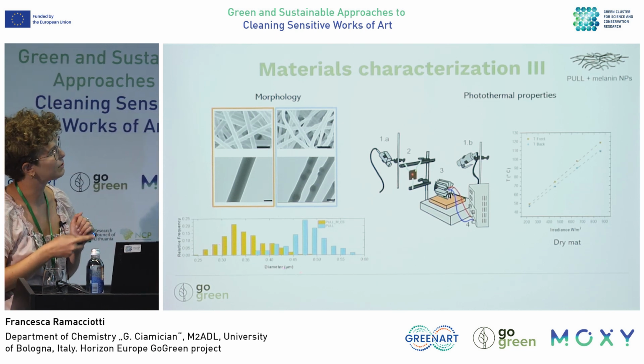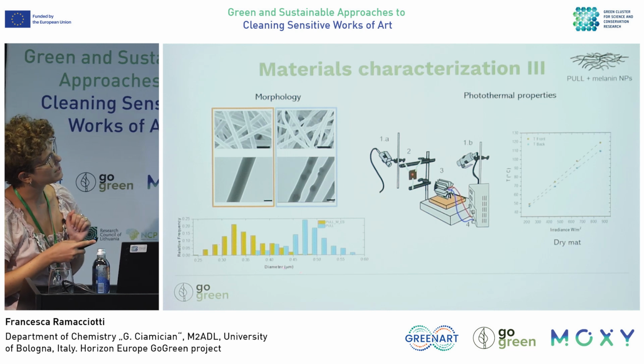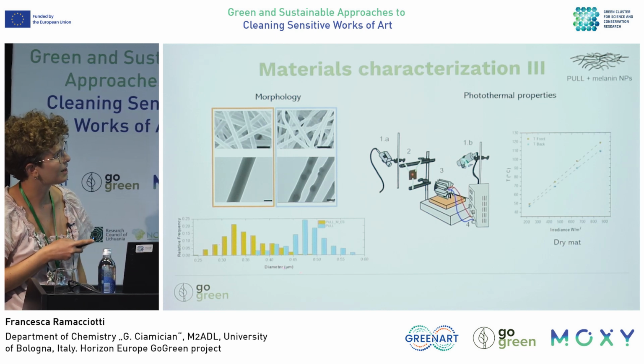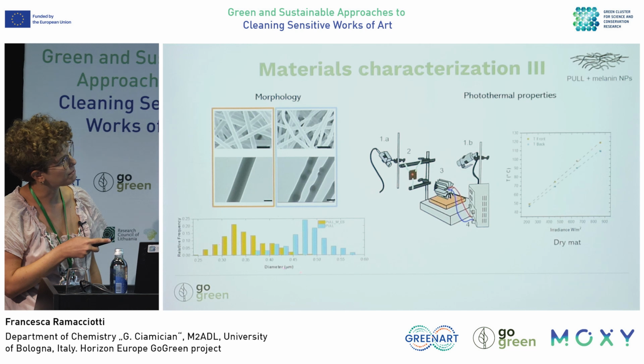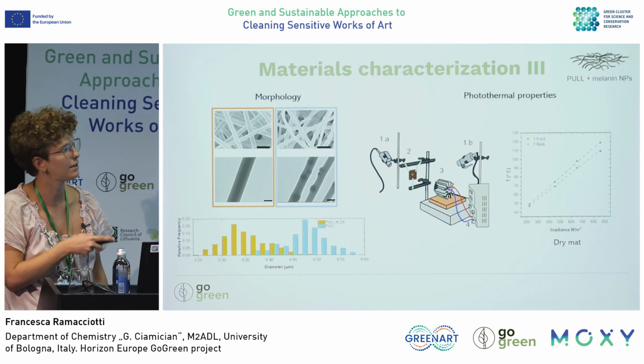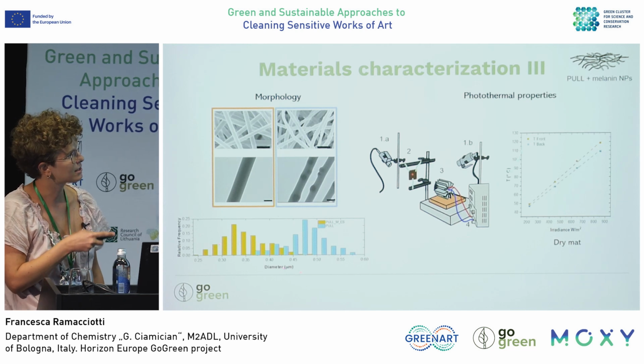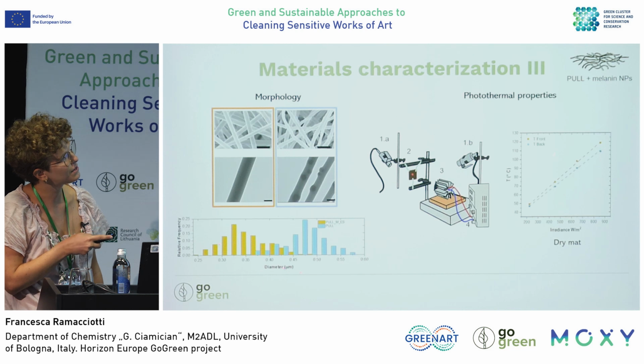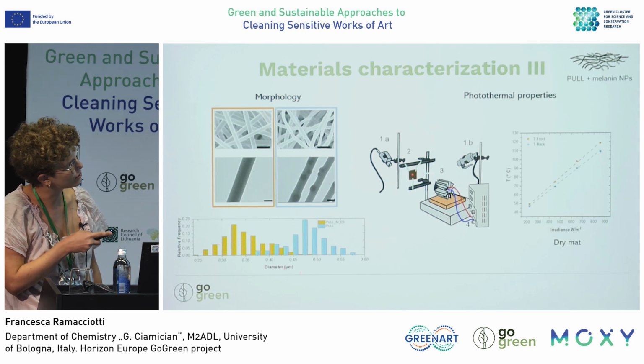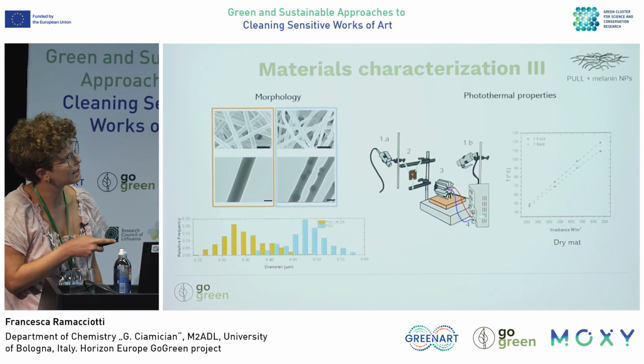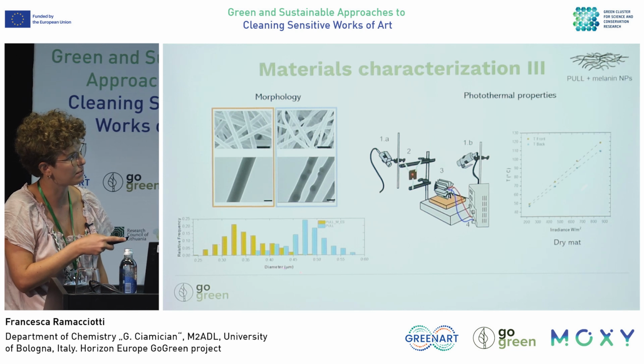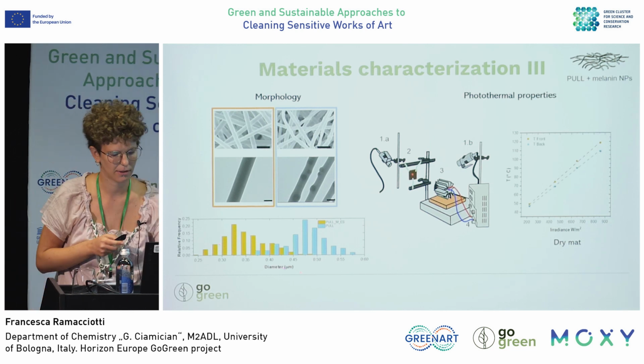And then we studied the photothermal properties. So once you irradiate your mat with the red light, you have an increase of temperature, and you have a linear correlation between the irradiance of the LED and the maximum temperature reached. And as you can see, generally the front, the side which is directly irradiated, has a higher temperature compared to the back. But this is a dry mat.